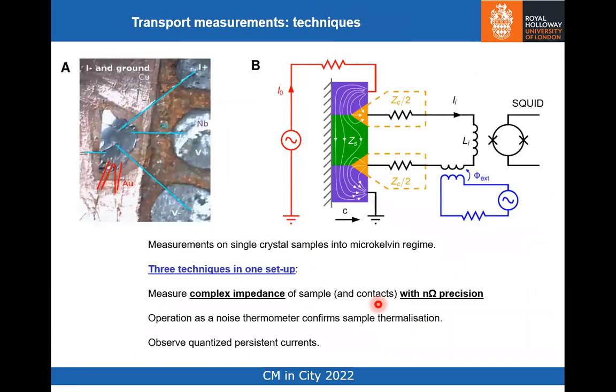Okay, so now on to transport. We're measuring transport initially on single crystal samples, using a two-stage SQUID as a very sensitive current amplifier. And without going too much into the technical details, we can measure three things with this setup. We can measure the complex impedance of the sample. So the sample impedance is denoted by Z_S.